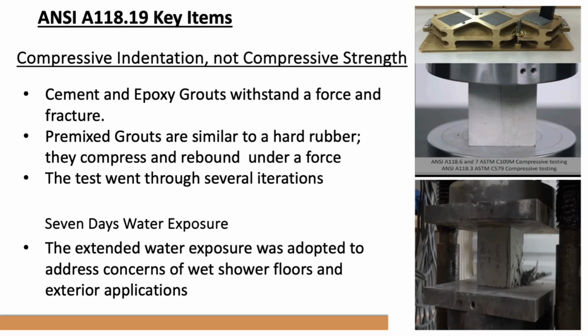They also do a 7 days water exposure test. So they do the extended water exposure. That was adopted to address concerns for wet shower floors and exterior applications to make sure we can put it in both interior, exterior, and, like we talked about, intermittent moisture areas.